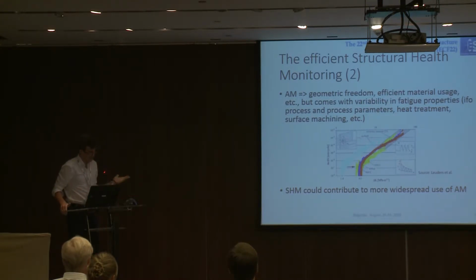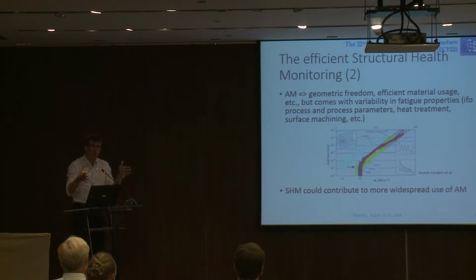Because additive manufacturing is very nice in the sense that it brings you additional geometric freedom, efficient material usage, etc. But it also comes with a certain number of drawbacks. One of these is that if you manufacture a component with additive manufacturing, there are so many things that can influence the fatigue properties of that component that you are actually quite unsure of what the final fatigue properties are. I've taken here an illustration of a study by Leuders et al., where you can see, depending on the different post-treatments that are applied or the as-built conditions, the crack growth curves are totally different.